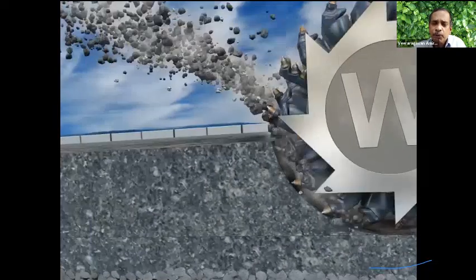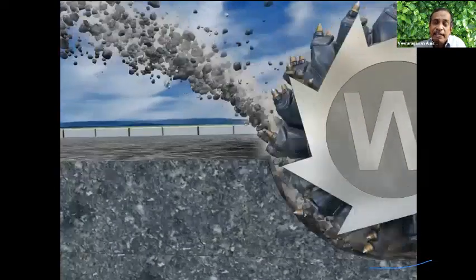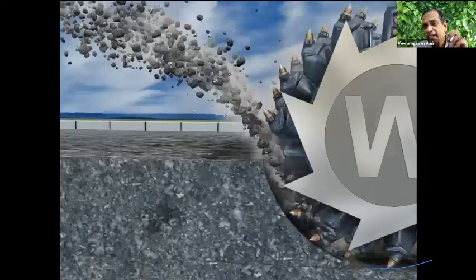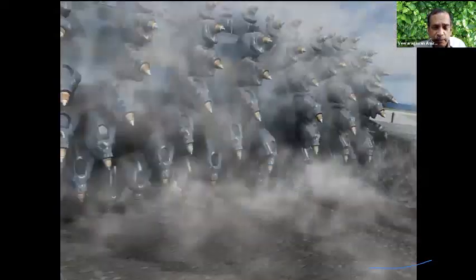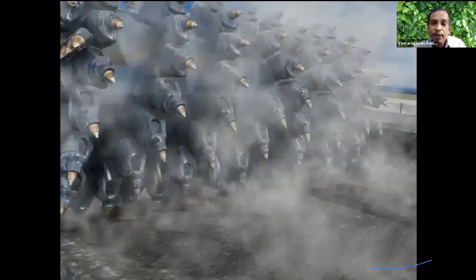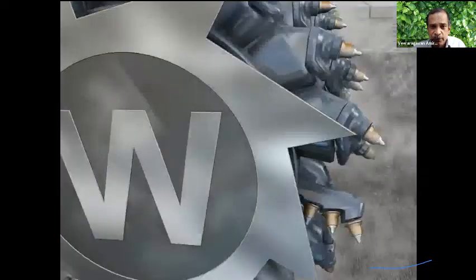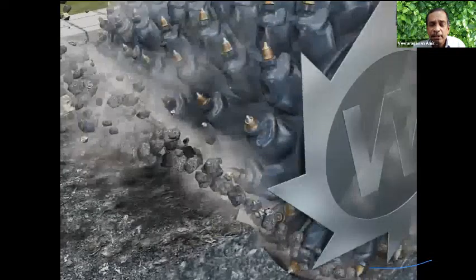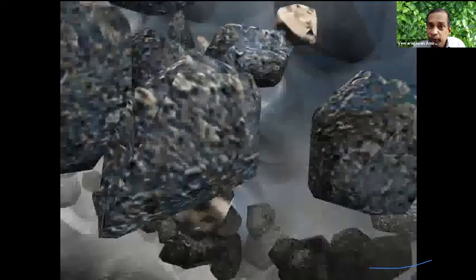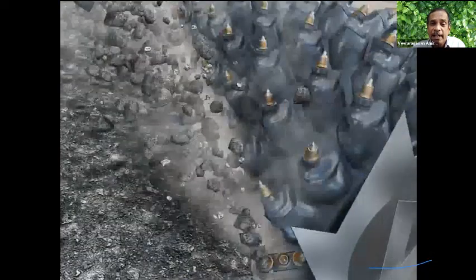What I'm trying to do is mill the material which has already been laid. Conventionally, what you do is you provide an overlay at the top. I don't want to do that. I want to mill the material and reuse it again. So when I mill and reuse the material, this milled material will have aged bitumen and aggregates. We can rejuvenate the material and use it again.